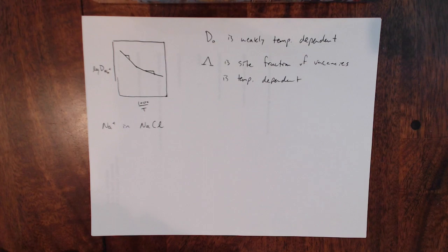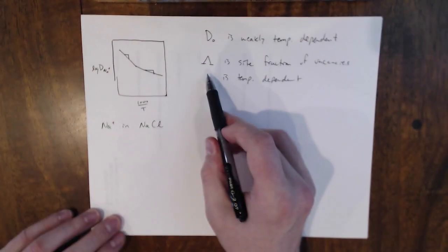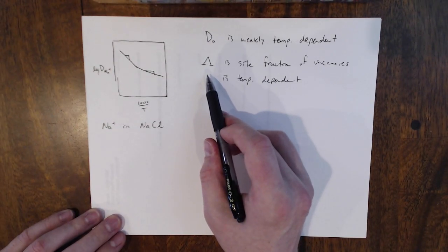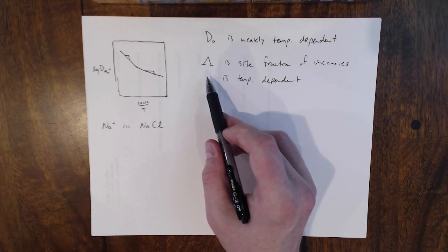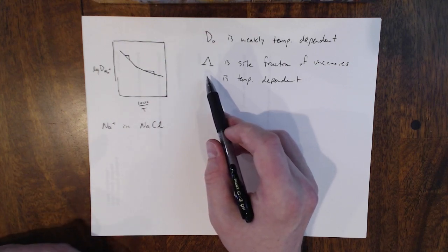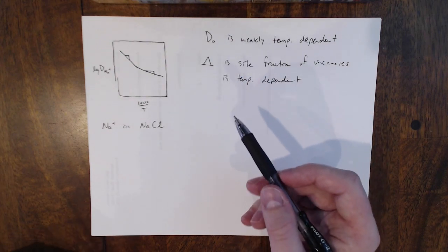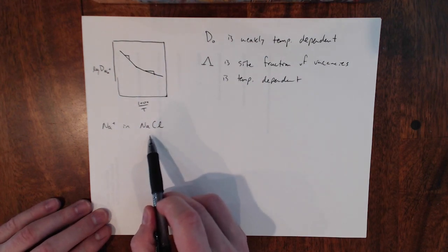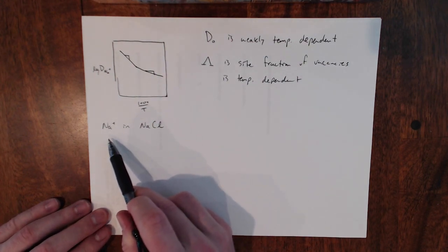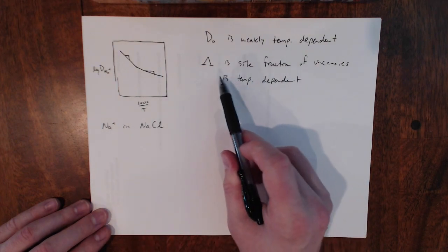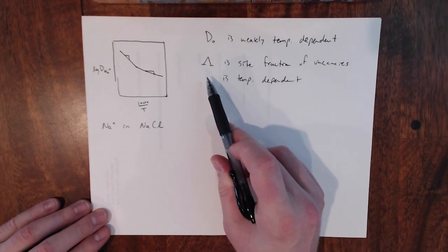So here, let's take a look at our vacancy concentration. If it's controlled by dopants or impurities, right? Then this expression here, our site fraction, would be dependent on how much we dope in as opposed to thermal activation, right? So changing in temperature, right? So if, for example, the sodium chloride that we have has some impurity that's causing sodium ion vacancies, then that would affect the vacancy concentration, right? So that's another thing that can affect this.